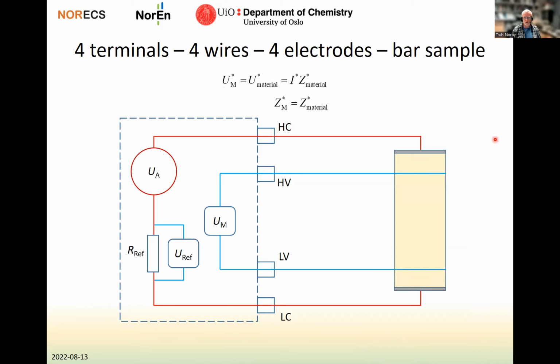But the 4-terminal, 4-wire, 4-electrodes sample is well recognized. It is typically employing a bar sample like this. Here the current is running through the entire sample, but the voltage is now picked up inside the material. There's no voltage drop here because there's no current running here. So now we do not measure the voltage in the wires, not in the contact electrodes here. We only get the impedance in the sample material between these 2 voltage probes. So this is a way to get a true sample material impedance.